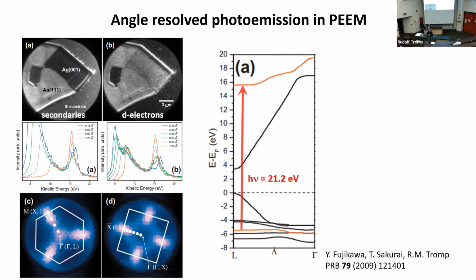Then once the electrons are in this unoccupied band, they can go out in the vacuum and we can detect them. If this photon energy had been 1 eV higher, then we would have been here just under this letter A. There's no bands there, so that photon could not have been absorbed because there would have been no state here where this electron could live for a little while before it goes into the vacuum, right? So people often think that in photoemission, you go from here directly into the vacuum. No, the sample doesn't know about the vacuum until the electron is actually up in the unoccupied band and can escape into the vacuum, right? So it's always this absorption from an occupied into an unoccupied state and then into the vacuum.